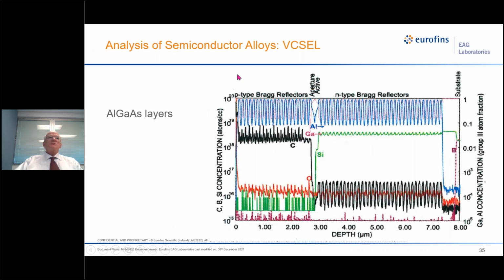So you talk about analysis of alloys. In this case, a semiconductor alloy, and this is a really great case. We analyzed a vertical cavity surface emitting laser, and it's made of a whole bunch of AlGaAs layers, like 100 of them. And we are able to quantify the aluminum levels in these layers thanks to another NIST standard. NIST has an aluminum gallium arsenide certified reference material. Actually, they have 2 of them. And using that, we quantify the aluminum concentration in all these layers.